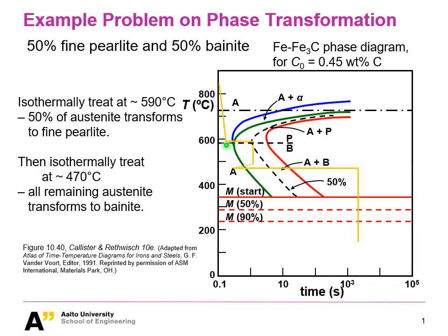And so you go to a rather low temperature with a fast cooling rate, and then you're just holding it. So you're doing an isothermal phase transformation, but you don't complete it. If you just went on and on, you would get fully across the red line and get fully fine pearlite, but it is not finished, and it stopped at 50% of pearlite. So at this point, you will have in your microstructure 50% of fine pearlite and the other 50% of gamma phase, austenite, because they didn't manage to have enough phase transformation yet. They're still there. But before they do anything, you just quench it.